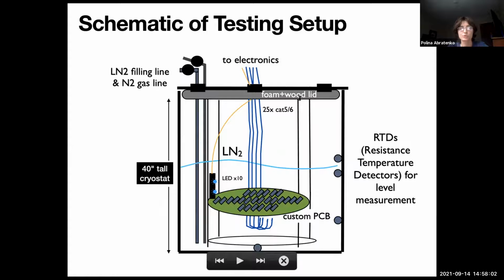So a little bit more detail about that is we use the 40-inch tall cryostat as our dark box. This had a foam and wood lid for insulation with holes cut through it to feed through the electronics, as well as the liquid nitrogen and gas nitrogen fill lines. On the structure connected to the lid, we have a custom PCB where we attach our boards. On one side of that, we have 10 LEDs. And on the side of this vessel, we have resistance temperature detectors to measure the level of liquid nitrogen when we fill.